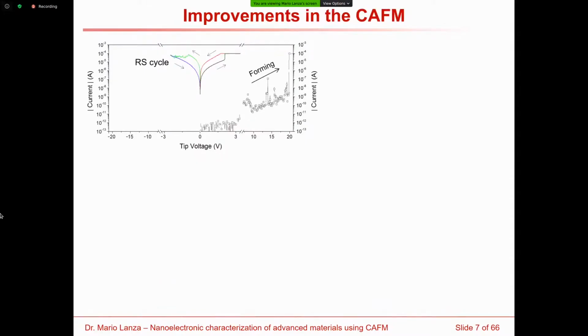So this study was possible because we modified the conductive AFM, because the standard conductive AFMs have very strong difficulties to measure this. And the reason is that in order to measure resistive switching, you need to apply high voltages to form the filament at the beginning. You need to measure high currents. The voltage stresses that you apply need to be current limited. So you need to apply a current limitation. And also you need to measure two polarities. So this is something one standard conductive AFM cannot do.